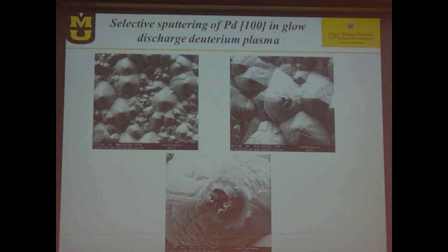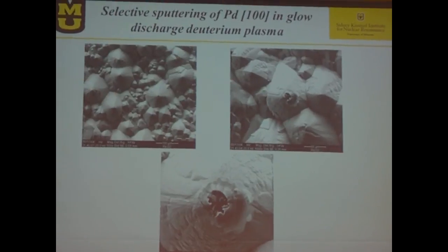The second direction that we are working on is glow discharge etching. Instead of chemical etching of the surface, we are exposing it to a bombardment of ions. We can do it with any gas, but with deuterium, the reproducibility rate is higher. And this is how the surface looks. Actually, after rolling, you get orientation 100, and since it's an FCC, you get pyramids with square base. So this is what we see.